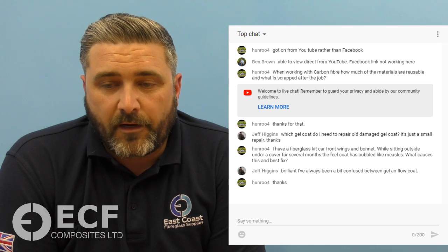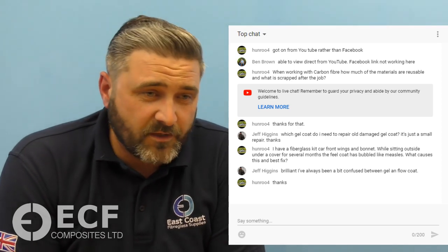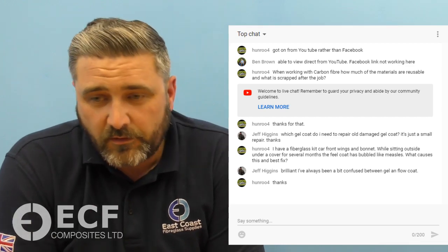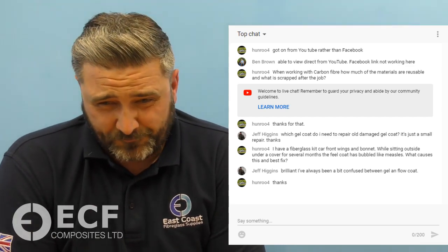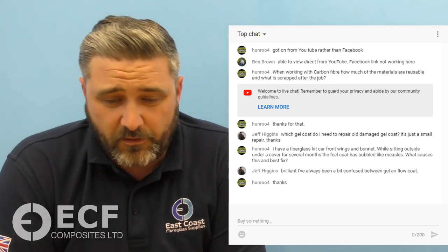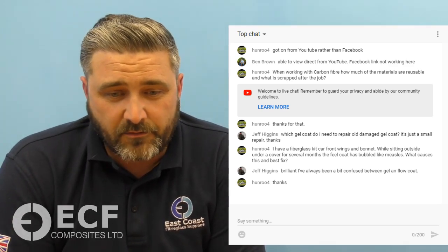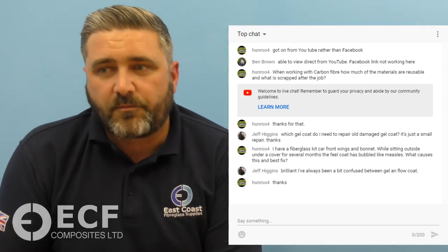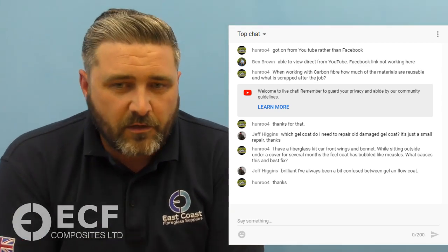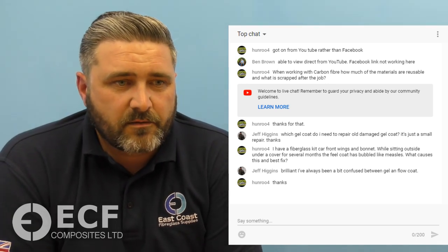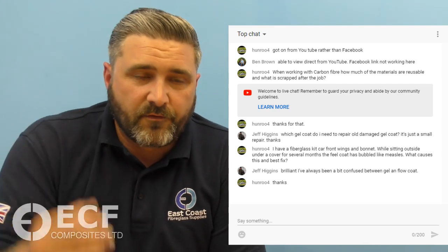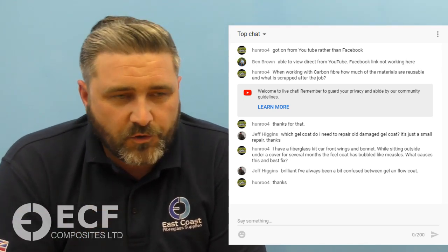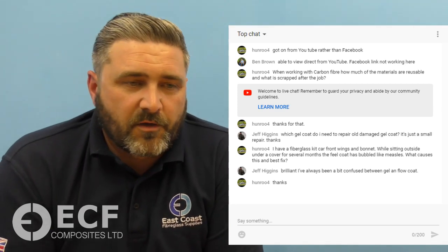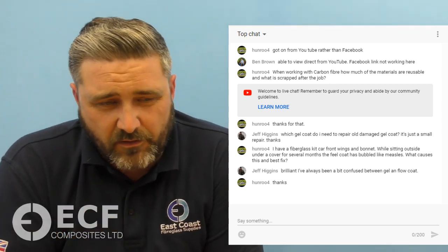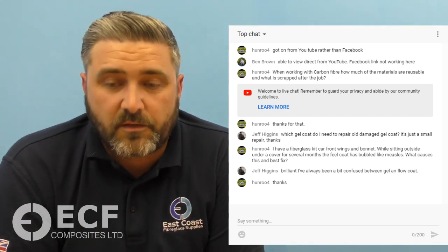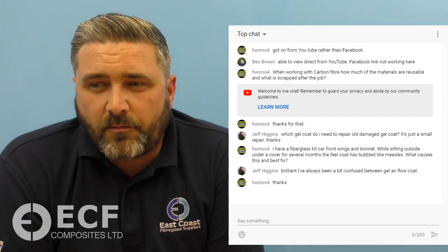So in most cases, if that happens, there's no real fix apart from just clean everything off with acetone, and starting again with that. To make the clean-up process easier, you can rub in some catalyst and then start peeling it out of the mould. If you're doing a roofing application, however, it's best to just clean it all up. It is sometimes tempting to mix up a highly catalysed batch of resin or top coat and then paint it over, but the chances are there'll be some areas that you'll miss that'll just stay tacky, and something like a roof that if you did that and trapped the uncured resin underneath, it would start to eat through because of the styrene being trapped in there, or the smell's going to go through into a property if it's a roof of a house.